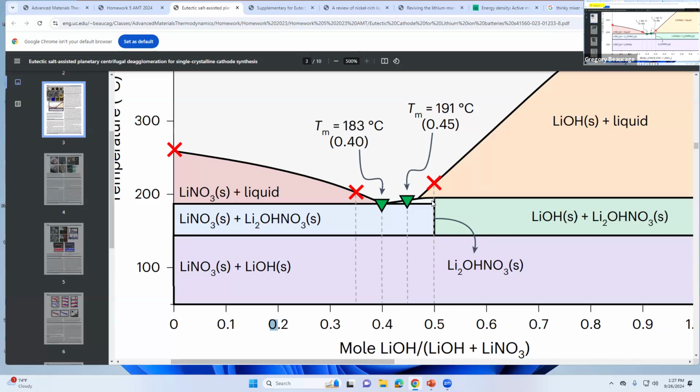In other words, if you look at the micrograph, that's what you should see, right? The point of this is to say, you start in here, you come down, you make the little particles, like 2% lithium hydroxide, then the liquid composition follows this, then you get to that point, and the liquid decomposes into liquid plus the intermediate phase. But as you go down here, there's more intermediate phase than there is liquid, so it's an intermediate phase matrix, but it's about like 30% liquid that reaches the eutectic and makes tiger stripes. So the thing should be 30%.